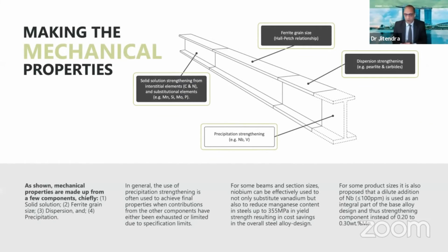So, a very quick overview of some of the basis of the mechanical properties. We know that when we make steels, we are relying metallurgically on a number of different mechanisms. That's solid solution strengthening, which is typically what we'll see from manganese, silicon, phosphorus. In these commodity grades, the reliance is on manganese as an element. We then have the Hall-Petch relationship, which is the ferrite grain size. And then we have dispersion strengthening, which is pearlite, which is more reliant on the level of carbon added to the steel. And then finally, precipitation strengthening, which is either from niobium or vanadium.